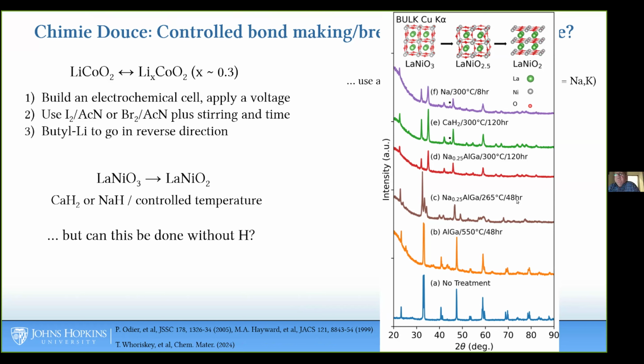Yeah, but let me interrupt at this moment, because those patterns you were showing, these were only low-angle patterns representing Bragg diffraction only. The point is that you've got structural information in between the Bragg peaks, and this information is about deviations from this ideal symmetry. And in fact, all the systems, when you take a look at the local structures, they are not that beautifully symmetric. They can deviate from symmetry very much. But you simply do not account for this because you do not use high Qs, do not use high resolution data.